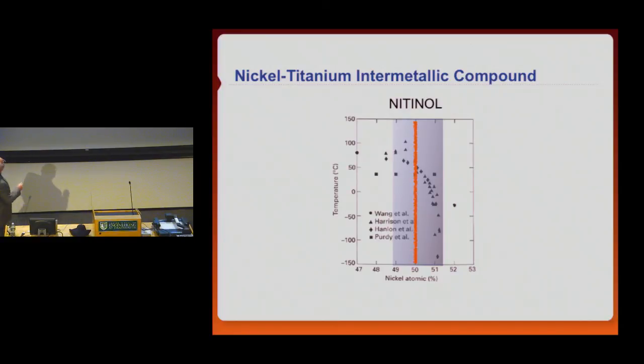And as you can see, in this range, you get transformation temperatures basically between 100 and minus 100 degrees, which tells you that when you melt this material and you are not dead on what you're looking for, you're off with your transformation temperature. So a 0.1% change in composition produces a temperature difference of 10 degrees from your targeted transformation temperature.